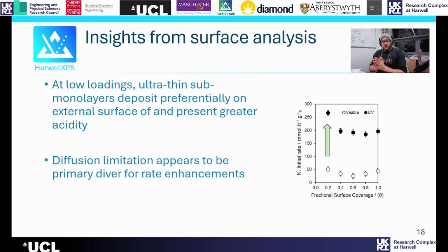So if at low loadings we have a more externally located active site, which also presents slightly greater acidity, this combination can now begin to explain our observed differences. Our reaction involves relatively sterically bulky compounds and a particularly large product, and an external active site is going to be free from diffusion limitations when we do our actual catalysis, while when we start to fill our pores with an active site, we are potentially going to start introducing some kind of pore diffusion limited kinetics into our catalytic reaction. And so once we normalize to the overall titanium mass, this is going to have an impact on our normalized initial rate once we have this diffusion to contend with.